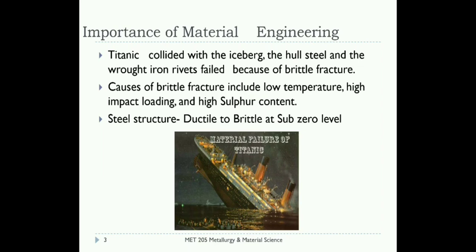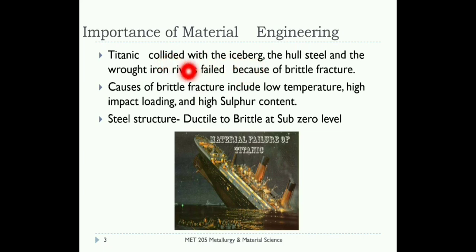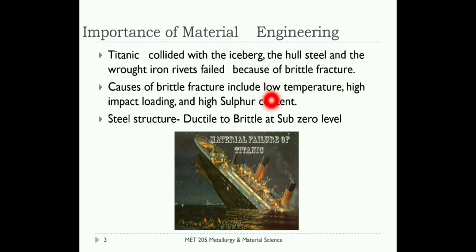The importance of material science in engineering is shown by the Titanic. Most of you might have seen the film — the failure of that particular ship was due to improper selection of material. The Titanic collided with an iceberg, and the hull steel and wrought iron rivets failed because of brittle fracture. The causes of brittle fracture were low temperature, high impact loading, and high sulfur content in the material.